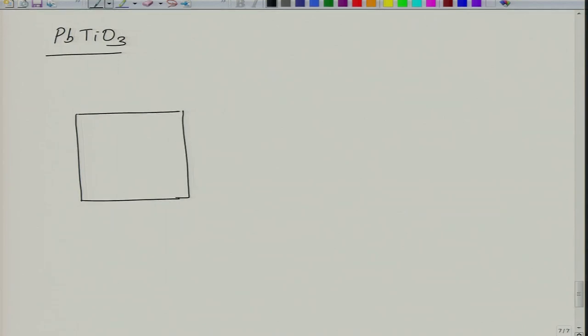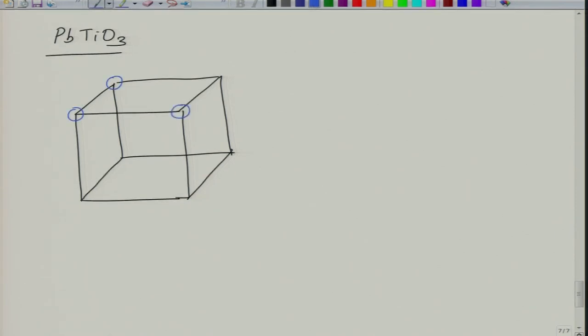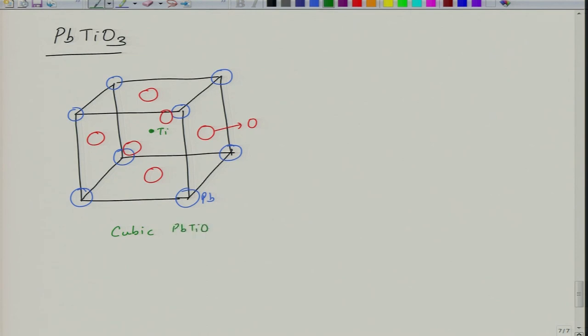So essentially what happens, if you take a model example of, let's say, PbTiO3, PbTiO3 has a perovskite structure. If you draw the structure of PbTiO3, these are all Pb ions. Let's draw the oxygen ions. These are oxygen ions. And then somewhere in between, we have a titanium ion. This is cubic PbTiO3 with P equal to 0. This is a centrosymmetric material. It doesn't have a polarization. It has a = b = c.